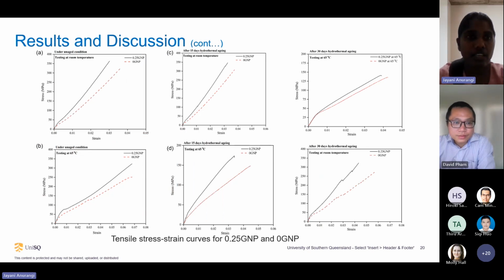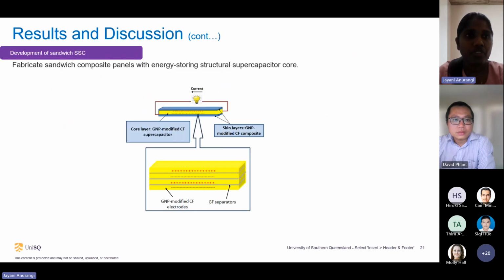Here you can see I evaluated the tensile properties without aging, after 15 days aging, and after 30 days aging. And also I evaluate the tensile properties at room temperature as well as elevated temperature at 65 Celsius. According to all these results, it was noticed that the GNP modified nanocomposite has higher structural properties than the control sample, which was fabricated without GNP. And also the GNP modified nanocomposite has high structural properties suitable for elevated temperature applications.